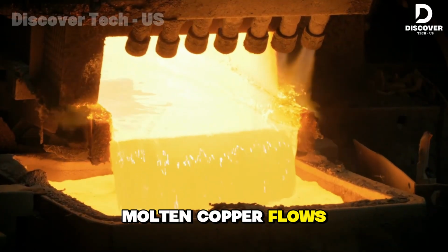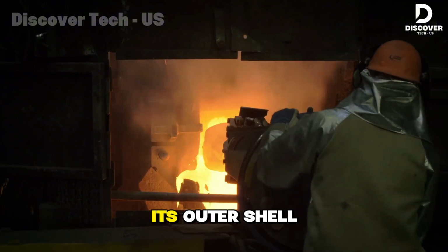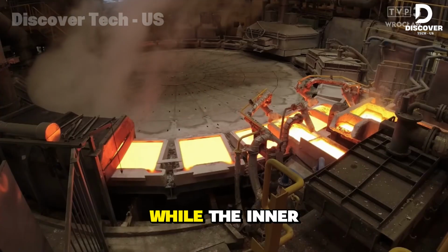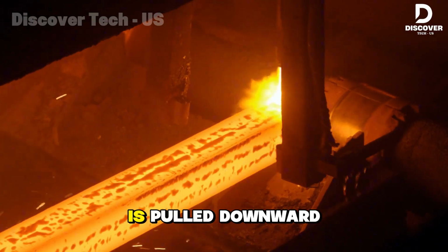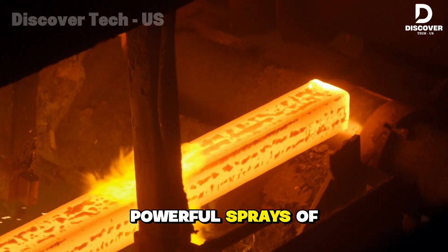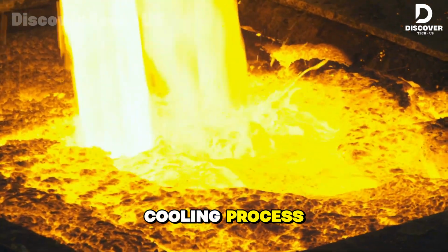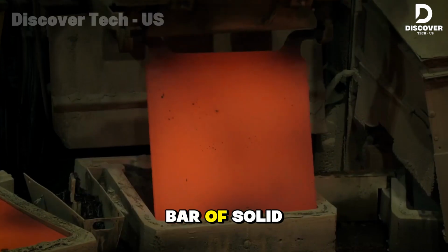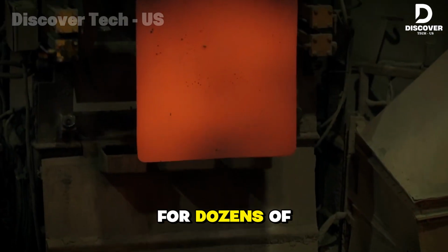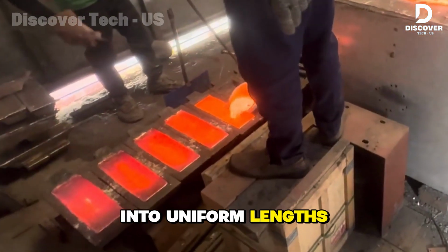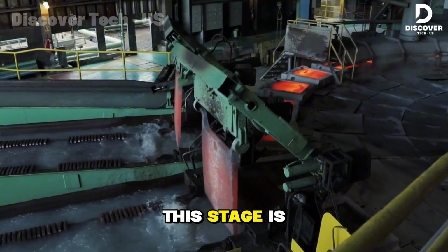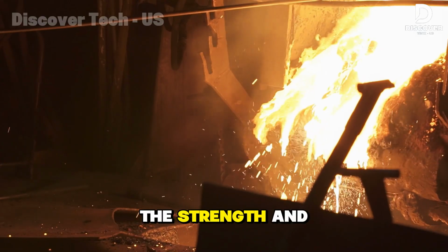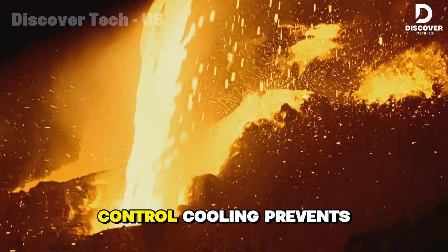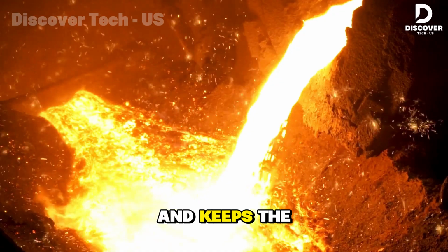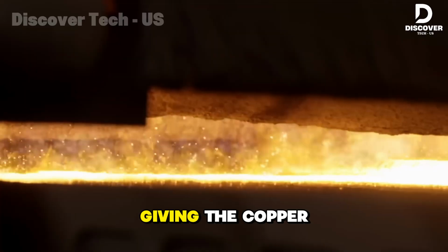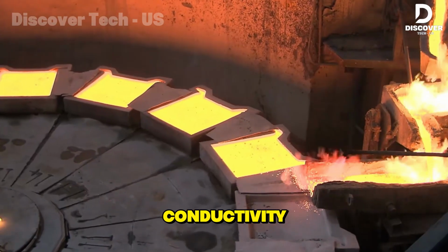Molten copper flows into a water-cooled mold. Its outer shell hardens instantly, while the inner core stays fluid as the strand is pulled downward. Powerful sprays of water complete the cooling process, producing a continuous bar of solid copper that can stretch for dozens of meters before being cut into uniform lengths. This stage is critical because it defines the strength and quality of the whole batch. Controlled cooling prevents internal cracks and keeps the grain structure perfectly aligned, giving the copper both durability and conductivity.